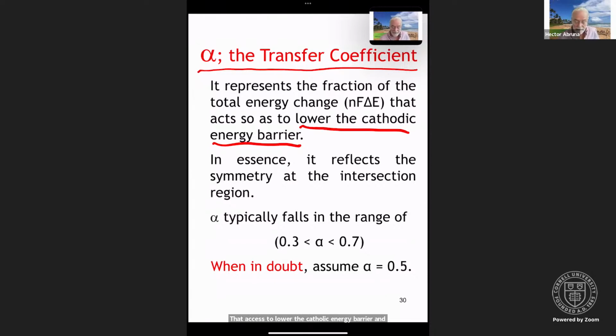It reflects the symmetry at the intersection region, meaning those two parabolas, if they approach the intersection region with the same slopes, alpha equals 0.5. However, you can have differences in the slopes, right? And so alpha can be less than 0.5. It will typically fall in the range of 0.3 to 0.7. When in doubt, which is often, assume it's 0.5. Okay? You can have some asymmetries in those potential energy surfaces, but more often than not, between 0.3 and 0.7 are very reasonable values.